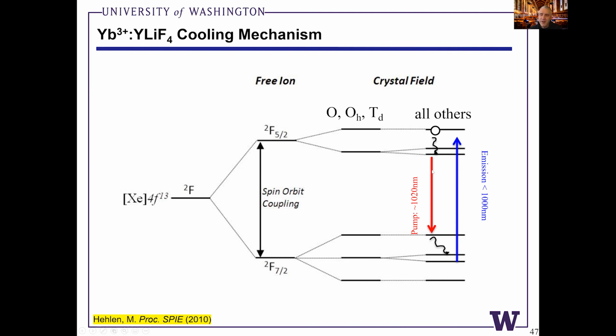The hole gets sent to the lower level, and it's optical phonons that upconvert this hole to higher energies. This is what's giving the thermal energy from the crystal. And then an electron can relax from this upper manifold, the doublet 2F5/2 configuration, down to this lower doublet 2F7/2 level, changing the configuration. And that's what causes the blue shift, just to explain it in a little bit more depth.